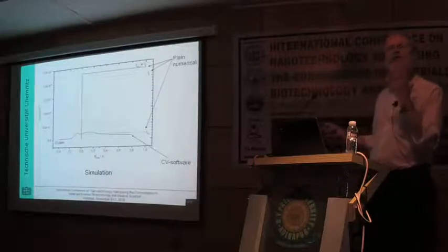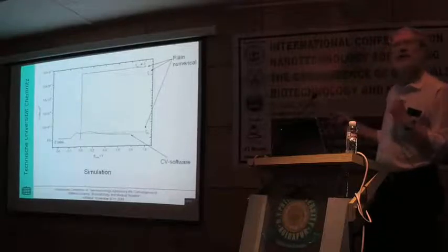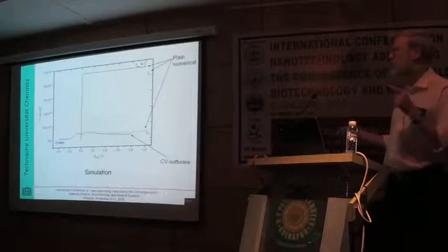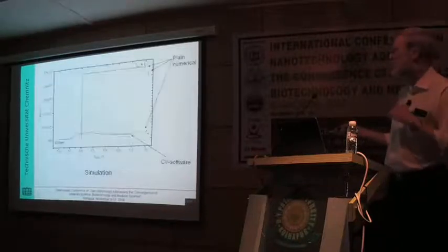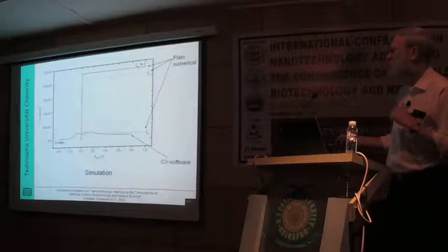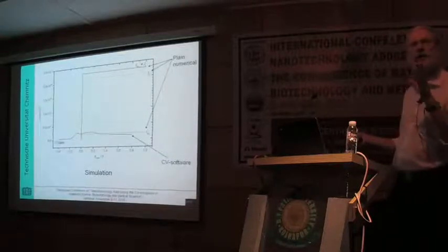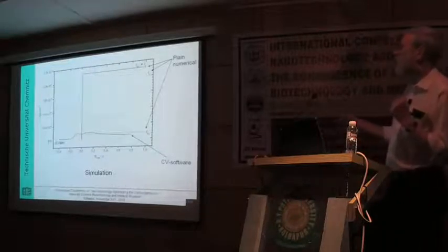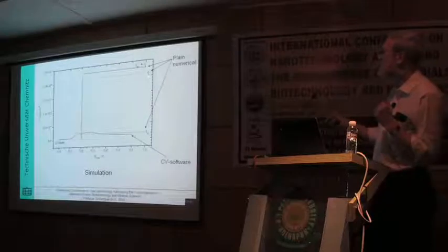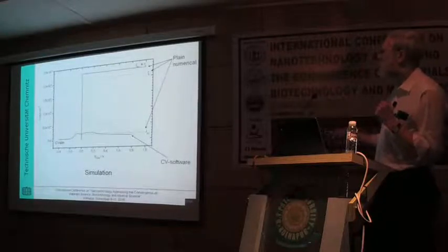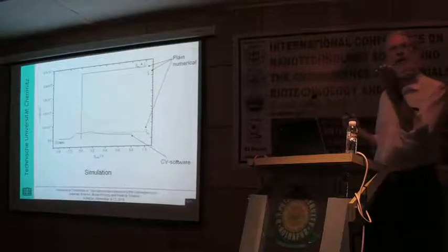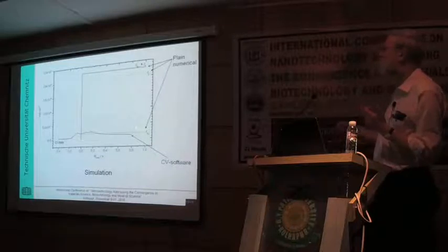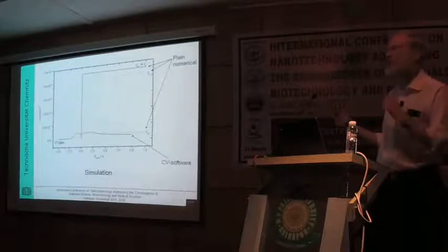And then I did an even cruder calculation. I just took a spreadsheet calculation. I calculated the amount of Faraday current, assuming this relationship as far as the electrode potential is concerned, shown here. These are just numbers. These are not exactly electrode potentials I have recorded with a particular material. I added to the Faraday response, shown here as a dotted line, the double layer charging current, because this manganese dioxide, of course, also has a double layer capacitance, but the double layer capacitance is much smaller than this Faraday charge storage capability.